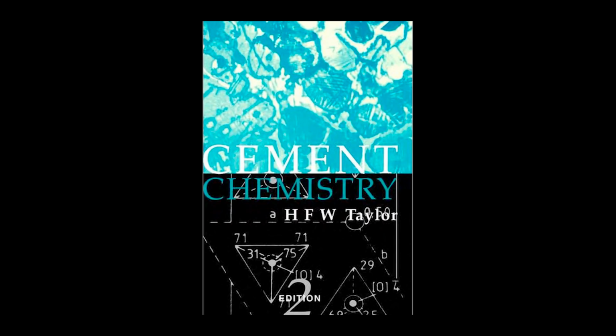So it sounds like ASR creates the weakness, and then DEF is the follow-up attack that finishes the structure off. It's a two-stage failure mechanism where the first chemical flaw primes the system for the second, physical failure. That's an excellent way to put it. It highlights that in durability, isolating one failure mode is often impossible. The chemical failure modes often conspire to accelerate collapse.